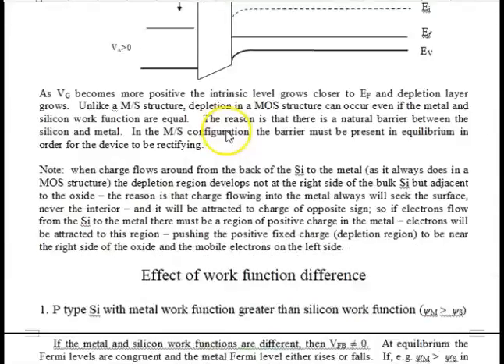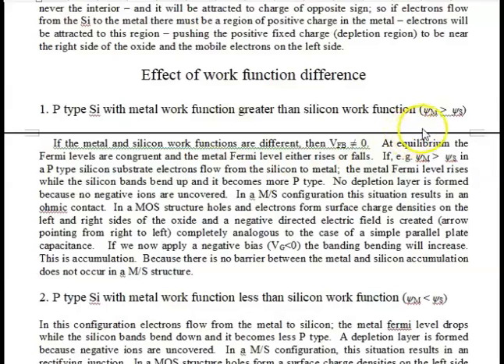This is the case if the work function difference is such that the metal work function is greater than the silicon work function. In P silicon, we have accumulation at equilibrium, and if we apply a negative bias to the gate, the band bending will increase up in the P side at the surface, and we go even further into accumulation. So in order to go into depletion, we have to make the gate voltage much more positive than we would if the metal work function were more quote-unquote normal.